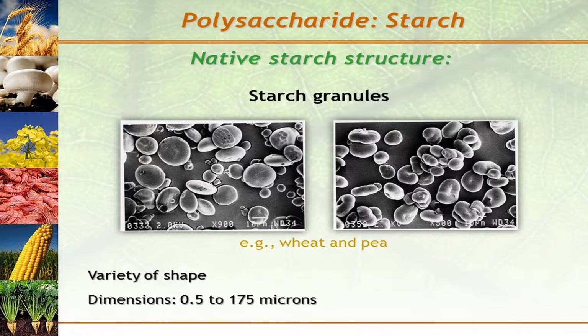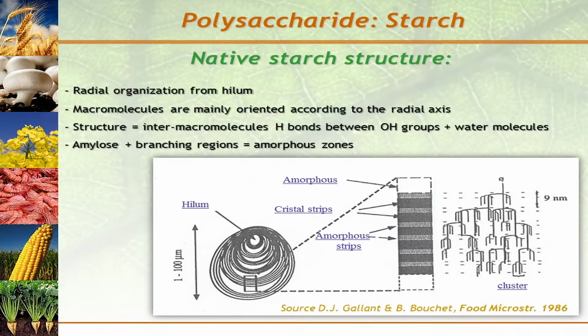of shapes and size. Here you have microscope photos of wheat and pea starch granules. And this granular structure of starch is shown here. You have this radial organization from the hilum of the granule, with the macromolecules mainly oriented according to this radial axis. And the superstructure of the granule is made of these inter-macromolecular hydrogen bonds between the OH groups of the chains, and also water molecules. And as previously mentioned, amylose and branching regions will give the amorphous regions, rings, whereas the amylopectin cluster will form these crystal strips or lamella.